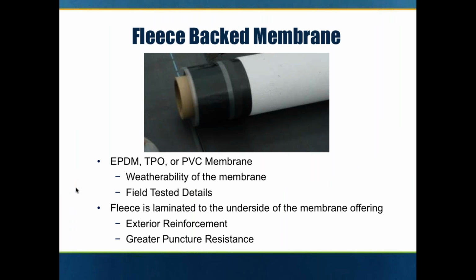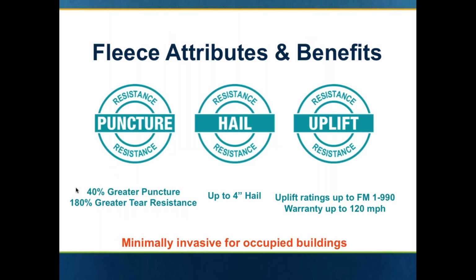So fleece back single plies. So you have EPDMs, TPOs, or PVCs for the weatherability of the membrane. You do have a laminated polyester fleece on the underside of the membrane. And that has many, many attributes that it's going to bring to that single ply system. It will enhance the puncture resistance, 40% on average greater puncture resistance than a bareback single ply system, and 180% greater tear resistance. It also greatly enhances the hail resistance, and there is testing up to 4-inch hail with fleece back systems. And for uplift ratings, it greatly enhances the uplift resistance along with a urethane adhesive.